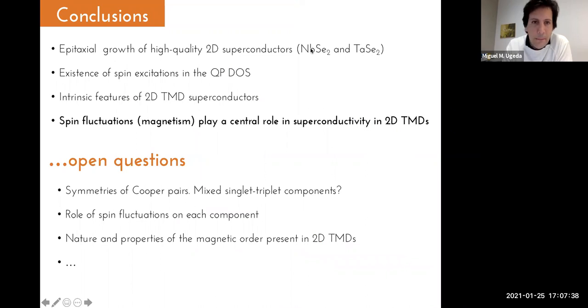Let me just say that we have achieved the epitaxial growth of these two superconductors, niobium diselenide and tantalum diselenide. We have proved the existence of spin excitations in the quasiparticle density of states. We have proved that these features are intrinsic to the superconducting state in this material, and not just in niobium diselenide, but in another TMD material. And basically the message to take home is that spin fluctuations, and in general, the presence of magnetism, must play a central role in the superconducting state in 2D materials. The open question yet is how, right?